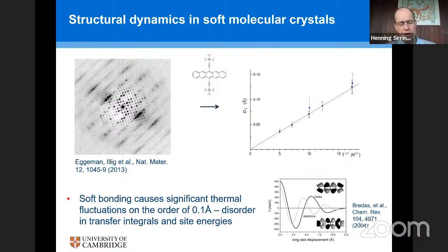So at room temperature, the molecules are fairly strongly vibrating around their equilibrium lattice positions, because the bonding in these materials is soft. It's not covalent bonding, but van der Waals bonding. So the molecular vibration amplitudes tend to be relatively large. And we developed a technique using these diffraction patterns to quantify the vibrational amplitudes. And you can see that on the right-hand side here. At room temperature, neighboring molecules in the unit cell vibrate against each other with amplitudes on the order of a few tenths of an angstrom. You could ask yourself whether that's a lot or whether that's not very relevant.